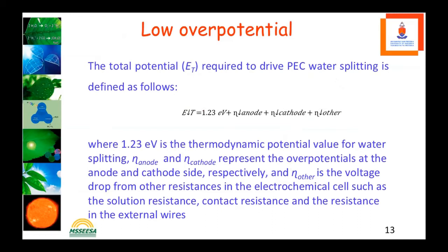Some of the properties that are necessary that we talked about, if we look at some of those previous slides, I will quickly go back to the previous slides. The requirements, we have spoken about the suitable band gap, and I've just explained that, and the band position, the low overpotentials. The total potential required to drive the photoelectrochemical water splitting is defined by this equation here, where 1.23 electron volts is the thermodynamic potential value for water splitting, and then eta anode and eta cathode represent the overpotentials at the anode and the cathode respectively. And eta other is the voltage drop from other resistances in the electrochemical cell, such as solution resistance, contact resistance, and many other resistances. And we must be aware that we are still working with a normal diode.